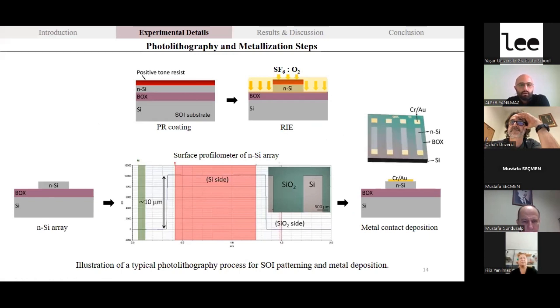When continuing with the fabrication side, photolithography is used to get the N-type silicon arrays. Here you can see the positive photoresist dropped on the N-type silicon side, and then to get the active layer shape, we use the reactive ion etching mechanism, and then we measured the thickness of the silicon side. Here you can see 10 micrometers as the desired thickness of our silicon-on-insulator substrate, and then we deposit the metal contact on the device. So you can see the final device shape with a size of 1 millimeter by 1 millimeter.